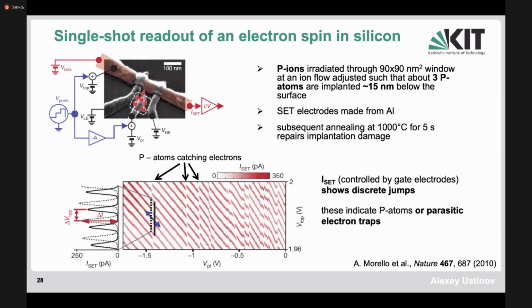So when the phosphorus ions were implanted, they of course sort of mechanically destroy the lattice. They go deep under the surface to a distance of about 15 nanometers, which depends on the beam energy, the acceleration beam, which accelerates phosphorus ions. And in order to restore the crystal order around the phosphorus ions, to make the crystal lattice regular and remove the disorder, one has to use thermal annealing. So basically, after the implantation, before depositing the metallic electrodes and forming all this device, the sample was annealed at 1000°C in order to repair the implantation damage. Of course, this is all probabilistic, but by increasing the temperature of the crystal, you make the atoms move, and then they eventually occupy the lowest energy states, which are associated with the periodic lattice.